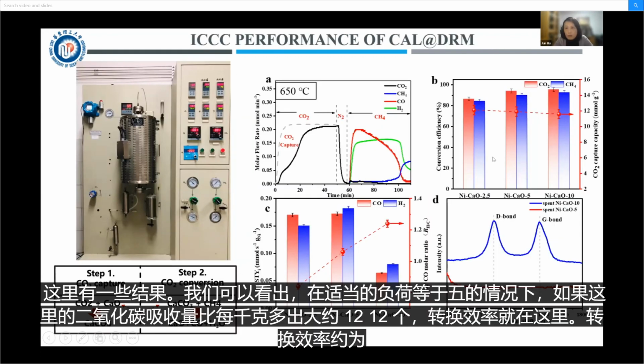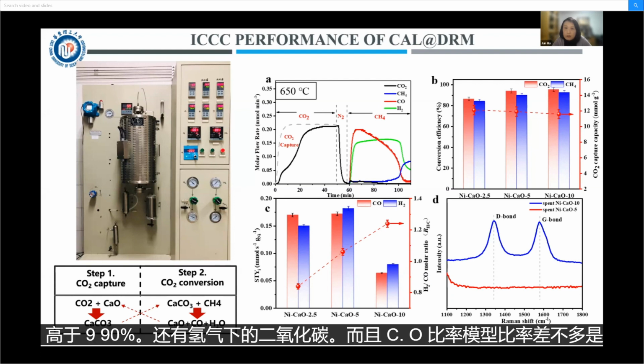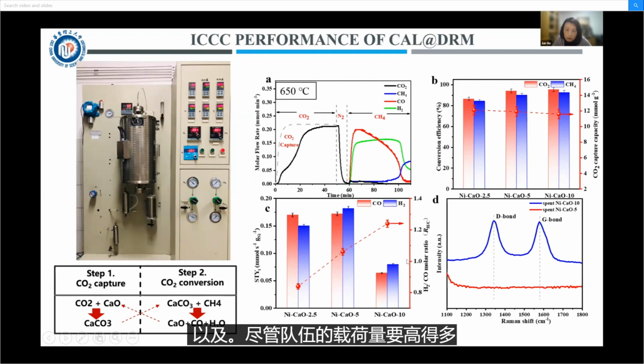And here are some results. Here we can see with proper nickel loading of 5, they showed the CO2 adsorption of about 12 mol per kilogram, and the conversion efficiency is higher than 90%, and the hydrogen to CO molar ratio is almost one.